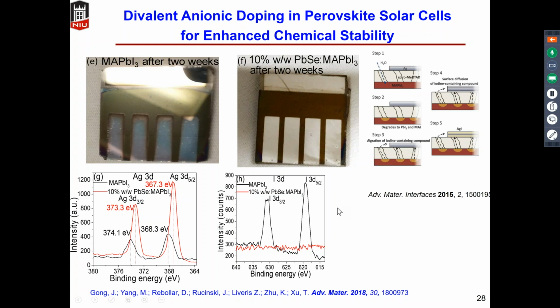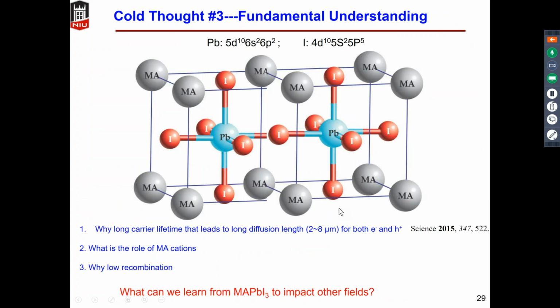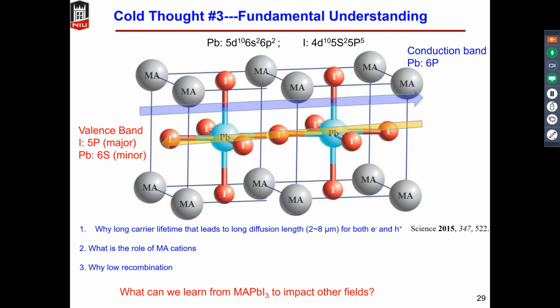So it is clear that chemical doping can help the chemical stability of perovskite layers. So our next thought was to enhance our fundamental understanding of this fascinating material. Just think about it, why does this material have such a long carrier lifetime? Because the valence band of this perovskite material resides mainly on the inorganic framework, contributed mainly from the iodine 5p orbital, and its conduction band also resides in the inorganic framework, contributed mainly from the lead 6p orbital. So both the conduction band and the valence band are in the same material.